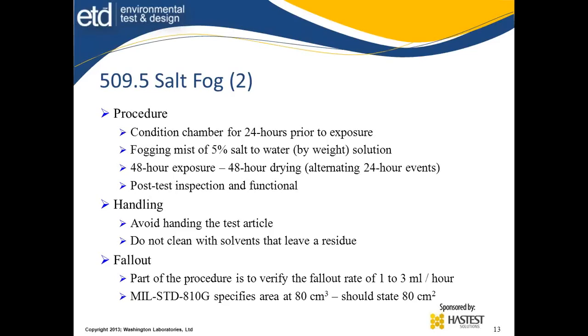You have to consider the fallout rate. It says the procedure is to verify a rate of 1 to 3 milliliters per hour. And by the way, MIL-STD-810G calls for an 80 cubic centimeter fallout rate. It should be 80 square centimeter. It's an area, not a volume. 810F had it correct. We changed to a cube function in G in error. So it's not a volume measurement, it's an area measurement, so it's a square.